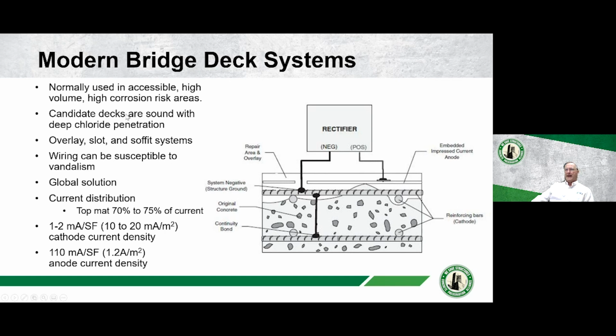So a candidate deck is going to be a sound concrete deck with deep chloride penetration. If you have chloride penetration from the top surface and it passes the reinforcing steel, it will be a good candidate for cathodic protection, because once it's past the steel there's nothing that can stop corrosion of the reinforcing steel other than cathodic protection. If you've got chlorides past the rebar, there's really not much else you can do except cathodic protection to stop it.